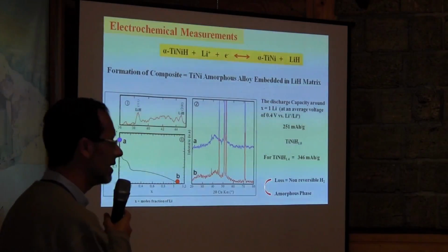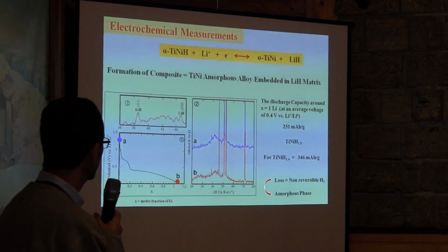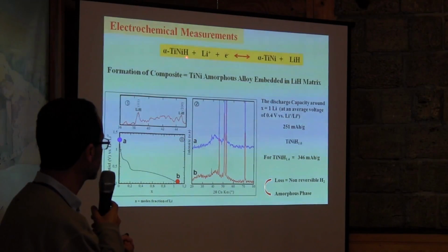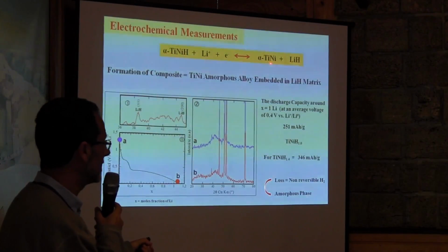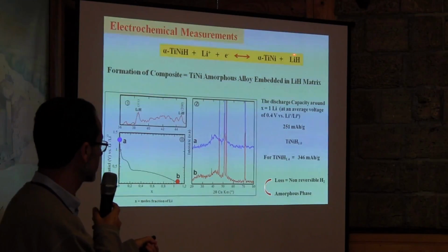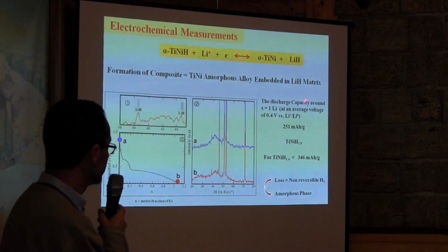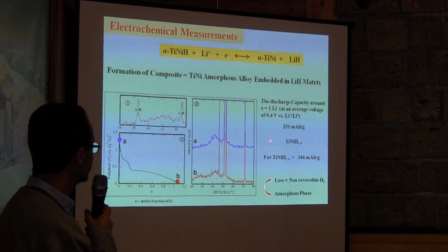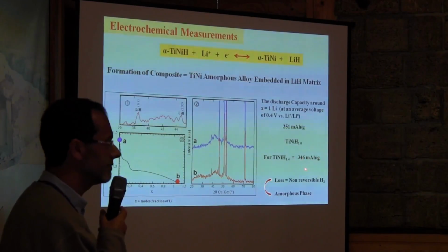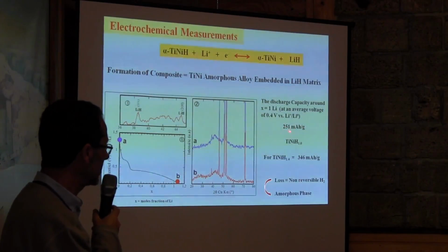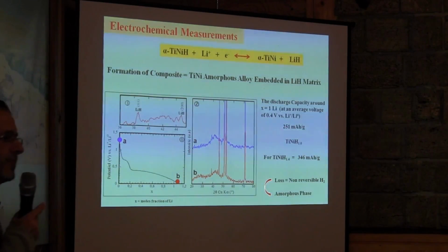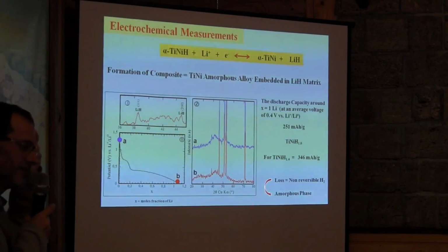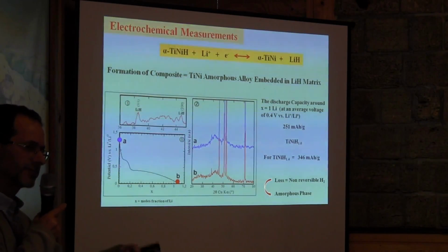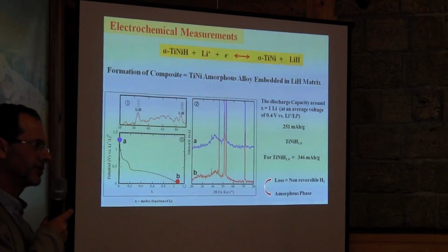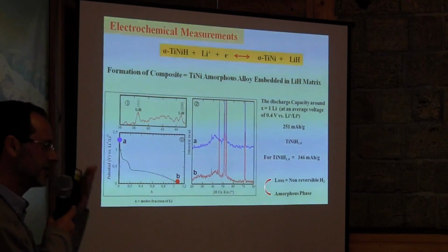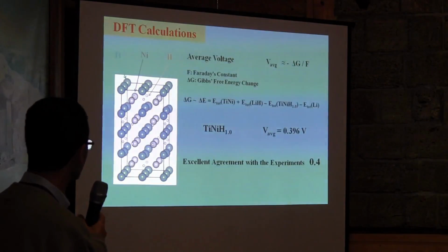Next one, please. Now we did electrochemical testing. So you can see alpha nickel titanium hydride plus lithium, and we obtain alpha nickel titanium plus lithium hydride. So now, what is the theoretical capacity of this compound? I think it's 346. But for our case, we obtained only 251. And we explain this, as I explained already in the first one, that amorphous phases don't release all the hydrogen. So it's very consistent. You can see it's always the same story.